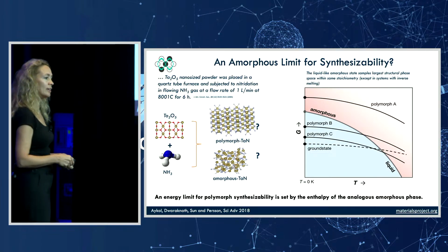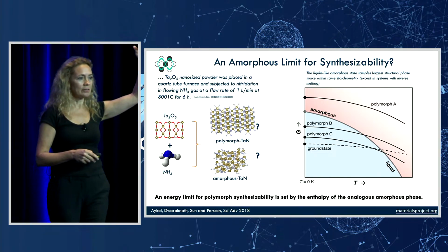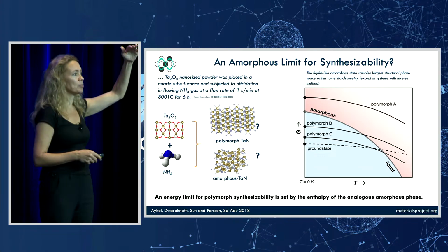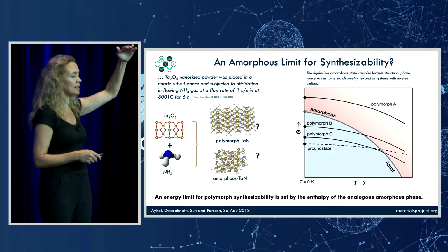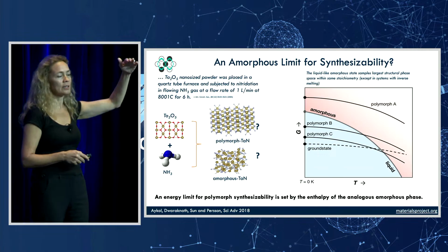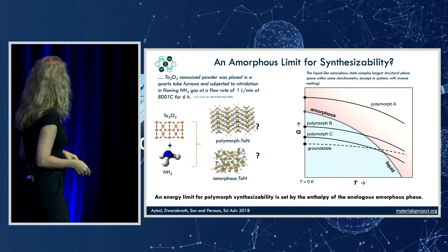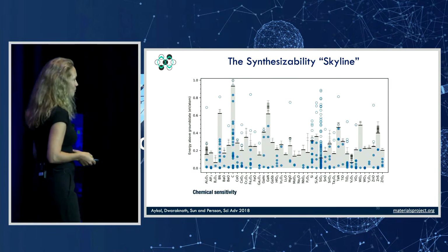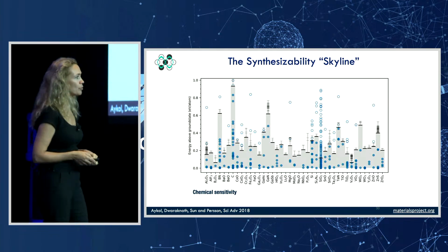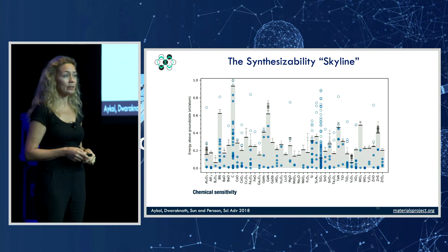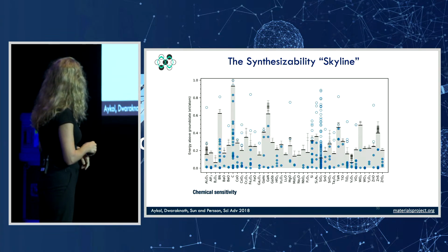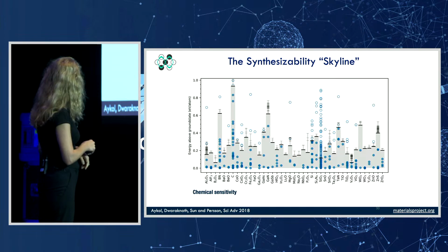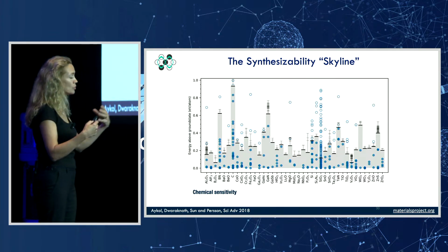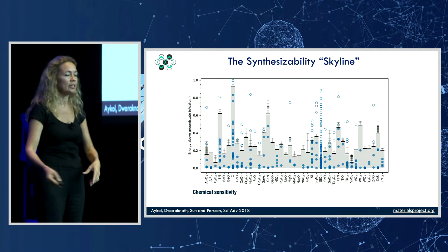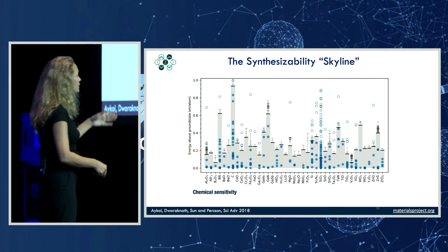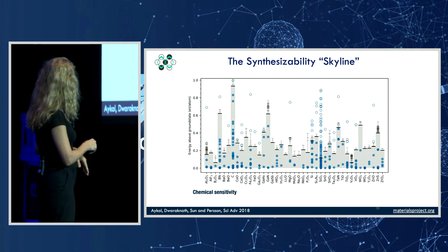So we hypothesize that a rigorous thermodynamic upper limit for synthesizability is set by the enthalpy of the analogous amorphous state of the material. So let's test that. We took 44 systems, oxides, nitrides, carbides, and calculated the amorphous enthalpy for these different systems. And you have to calculate once for every single different chemistry. And also, if you do it at different pressures, that also has to be a different one. But this is just ambient pressure.